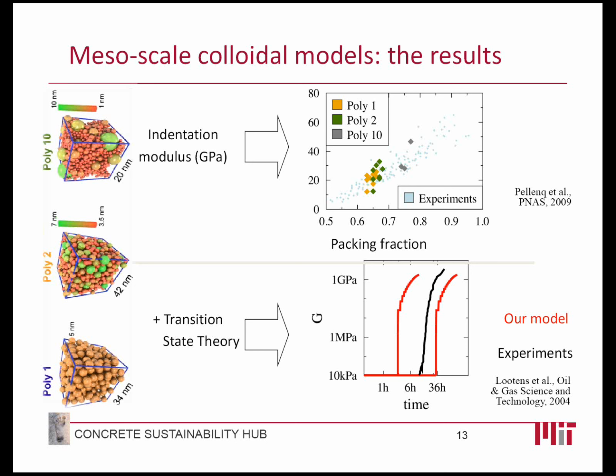At the same time, on top of this grain-grain interaction description, we can use transition state theory to predict the evolution of mechanical properties, here the shear modulus as a function of time. This is the type of simulation measurement we can do. You see that we have two red lines for our model, and the experiment is in black. The difference between the two simulation curves is linked with how strong the interaction between the grains is. So we predict the mechanical properties from interaction between grains designed at the very small scales from atoms. Next.